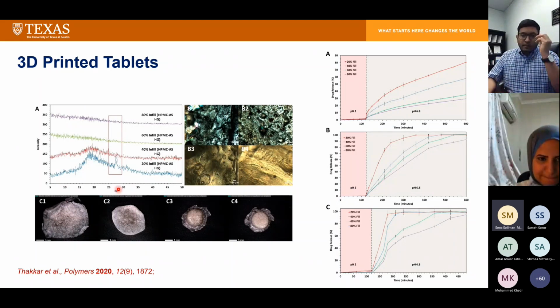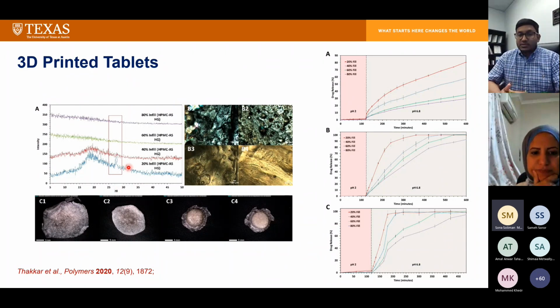We also conducted advanced analysis during the dissolution studies to see whether there was evidence of recrystallization with drug content 20%, and we found that there was no evidence of drug recrystallization when the samples were withdrawn during the dissolution studies. That confirmed that our adopted technology produced the drug fully in its amorphous form. Right, so this was a good example, but I'm not going into detail because we have already published this paper. If you're interested to read, you're more than welcome to obtain it from this link.